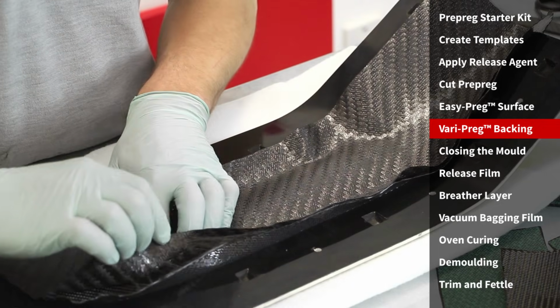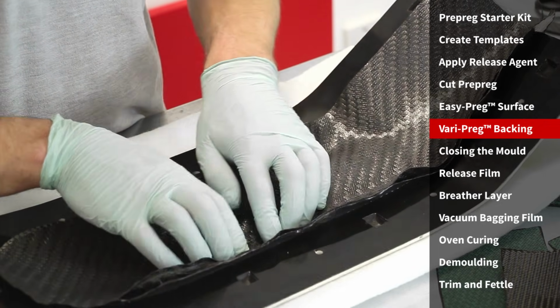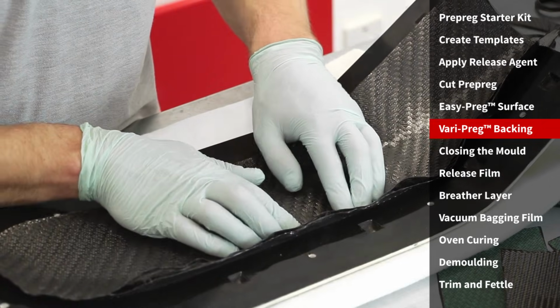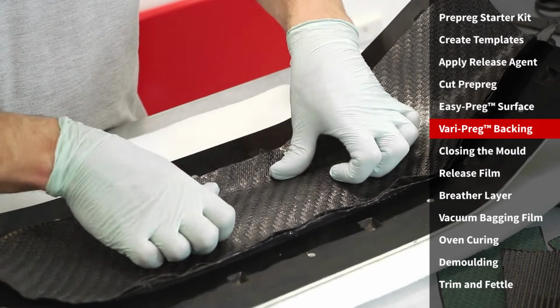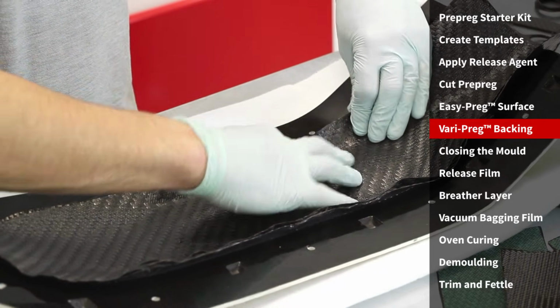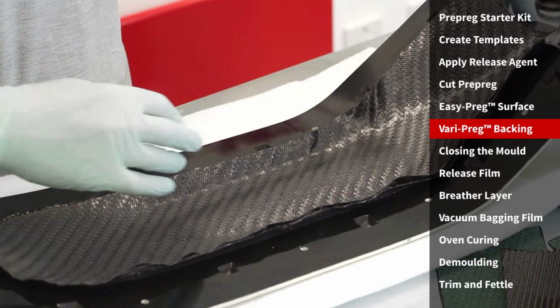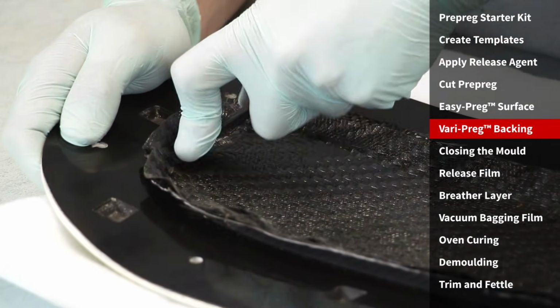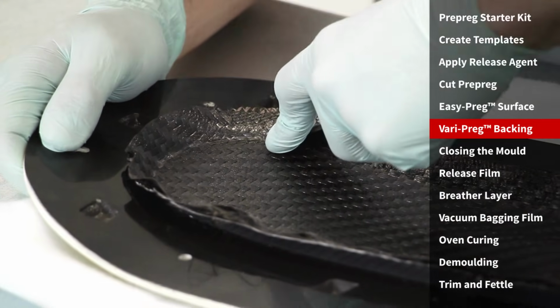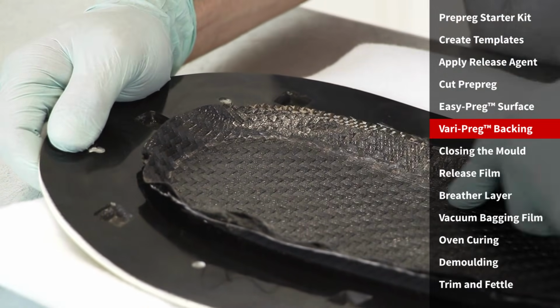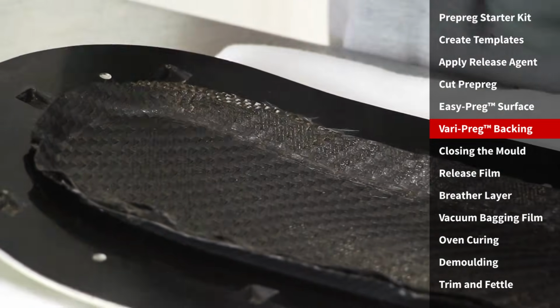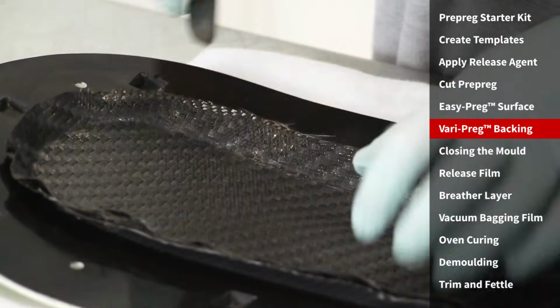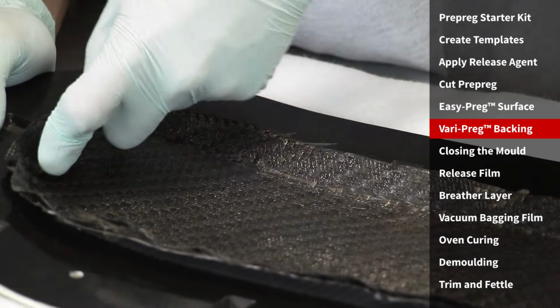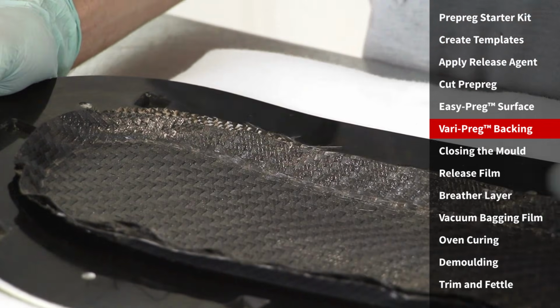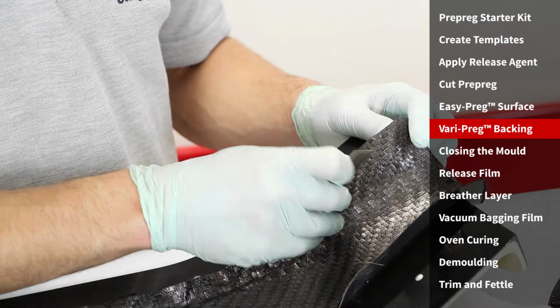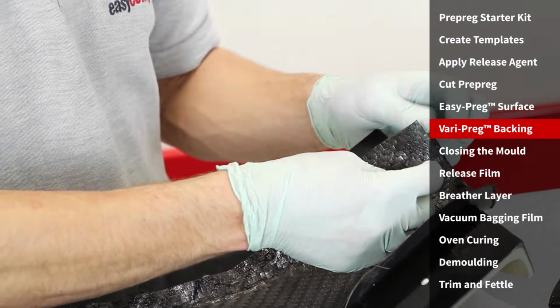Prepreg laminating tools are often used to aid the laminating process. These normally consist of a range of blunt implements, often hand-shaped by the laminator from plastic or even carbon fibre. These are then used to push, manipulate and burnish the material firmly against the mould surface. If ever there is a fault in a final component, 9 times out of 10 it would be small pinholes in a corner. This is as a result of material bridging. You must pay extra attention to corners, ensuring that there are no voids between the mould surface and the prepreg.